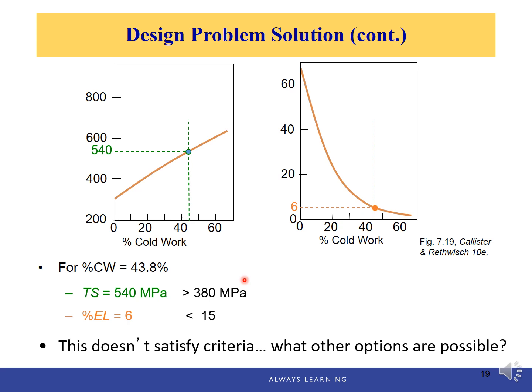Well, how about this? We need to decrease the amount of cold work, it seems, right? Because at this amount of cold work, the ductility is much lower than what we need. So how about we take steps? The initial diameter is 10, the final one is 7.5. Instead of doing one-step drawing, how about we find an intermediate diameter greater than 7.5 and do cold drawing once.